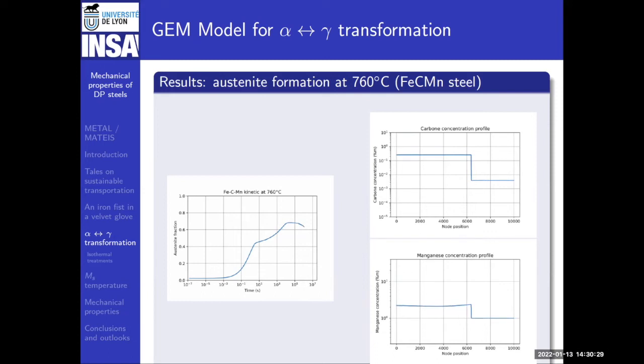But this evolution is due to many things occurring at the same time. And we can understand, and this is what the model predicts, only if at the same time we plot the carbon concentration profile and the manganese concentration profile. The whole complexity of the problem is due to the fact that one element is diffusing extremely fast and one is diffusing much slower, 10,000 times slower. So what happens?